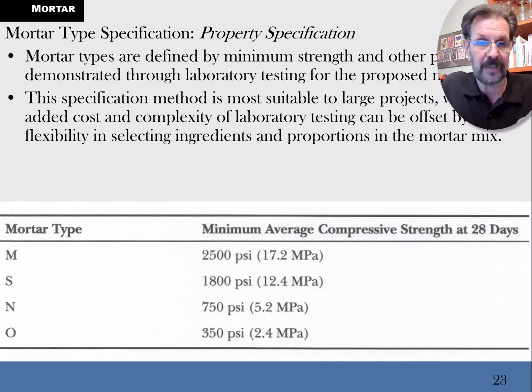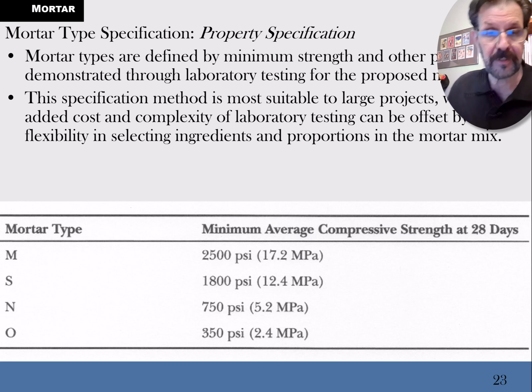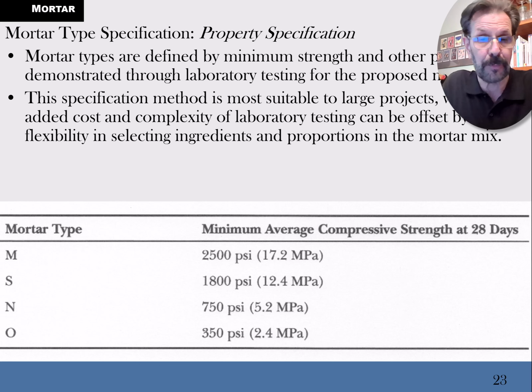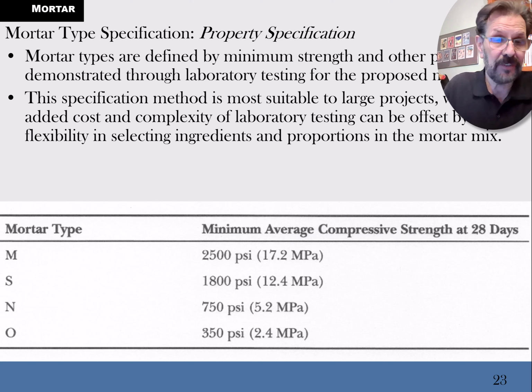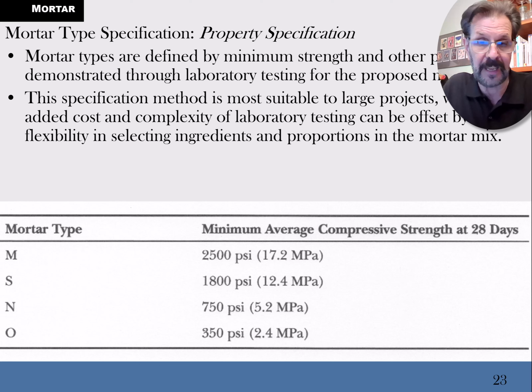And then when you get to a higher strength, maybe 5,000, and with precast bridge girders and stuff, we're looking at 6, 7, sometimes 8,000 psi. Here, the Type M is not too bad at 2,500, still pretty weak. Type S is kind of pathetic compared to concrete, and when you get down to N and O, we're looking at embarrassing numbers for strength. Not very strong at all.